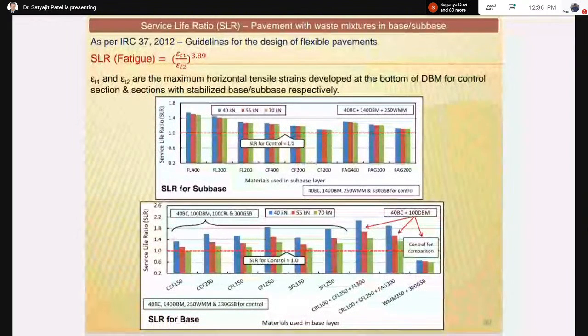control material. So whatever elastic modulus you have obtained from the FWD, that elastic modulus can be used in the Plaxis analysis to obtain the strength, the horizontal tensile strain or vertical compressive strain. From this, the service life ratio has been obtained. So if you see here, service life ratio is 1 for the control material. With respect to 1, your service life has been obtained up to a maximum of 1.5.